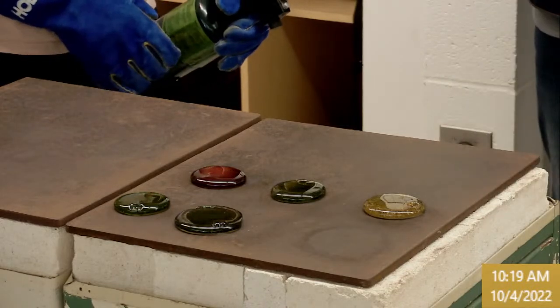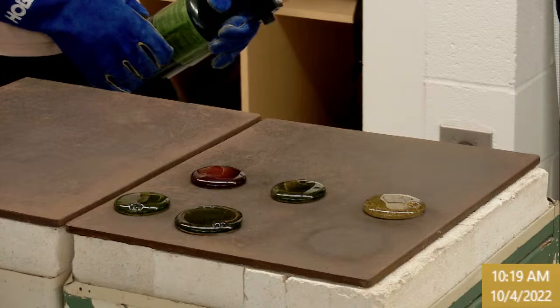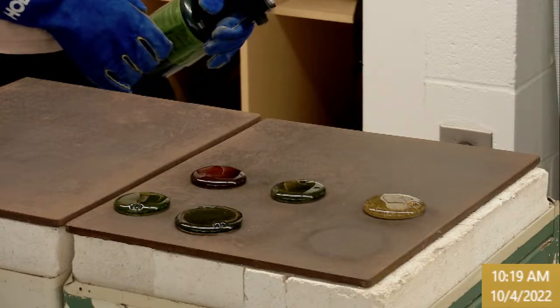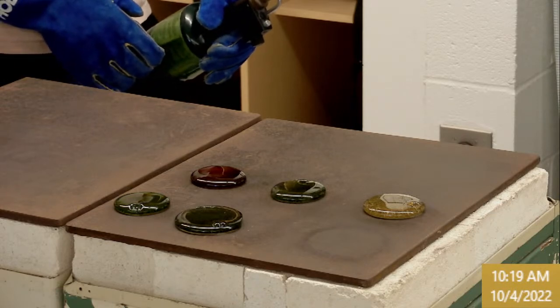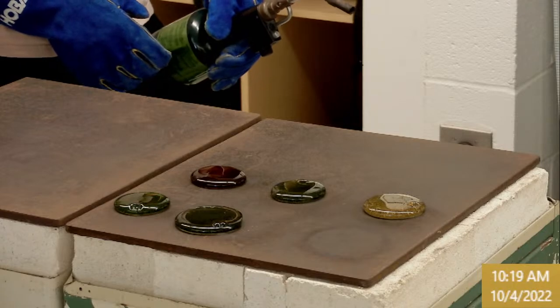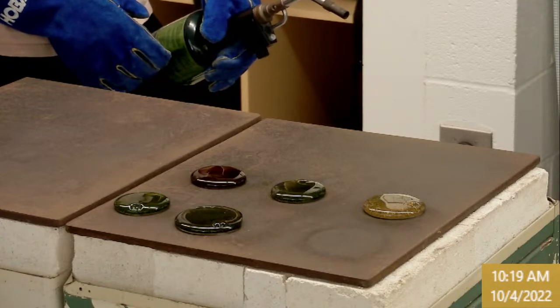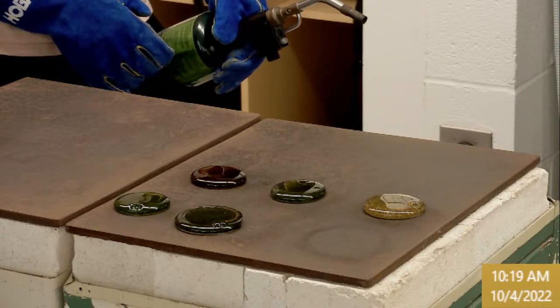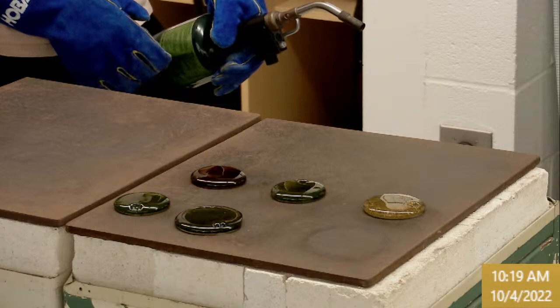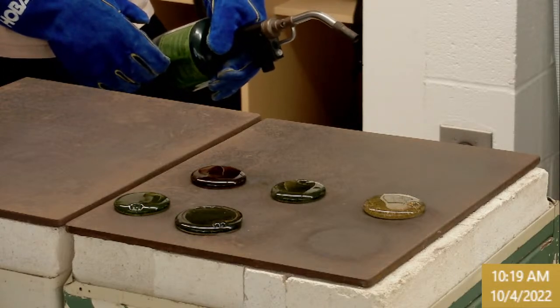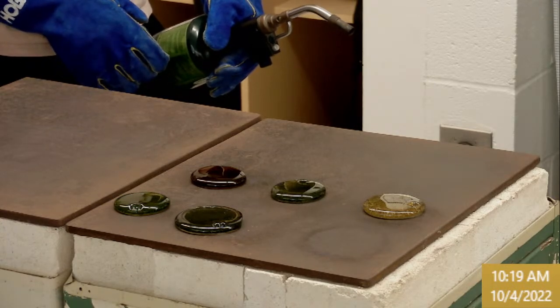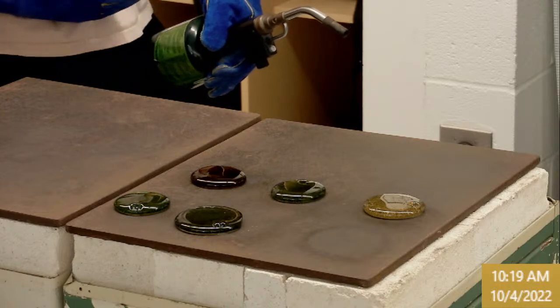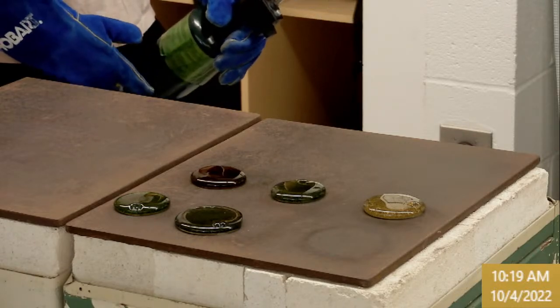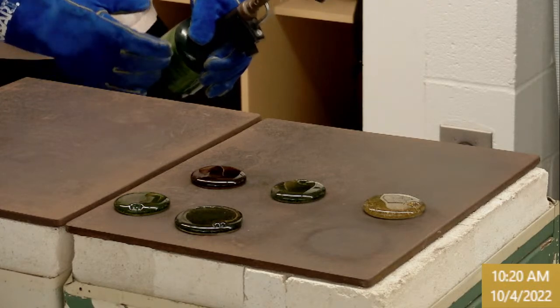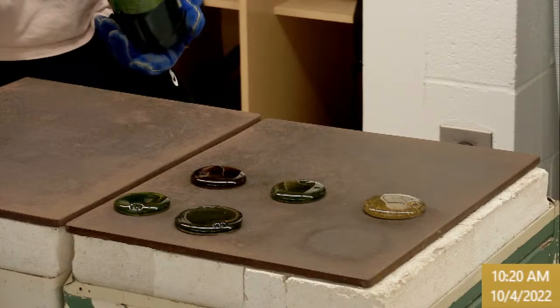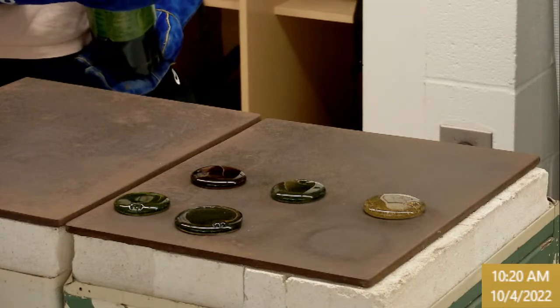The next one is composition G. So this is a Fisher silica. I think this might be our first example of a high purity silica. So Fisher silica, sodium carbonate, calcium carbonate, 52 26, pretty standard. Slightly higher on the flux loading, just a little bit. And 0.1 grams of manganese. So this one, because we're using the pure silica, should hopefully be our truest purple color, since there's not a lot of iron. So we'll keep an eye on that, see when that color finally strikes. In the glass industry they call it the striking temperature of the glass. The final color develops at a certain temperature. So, all right, so G2.